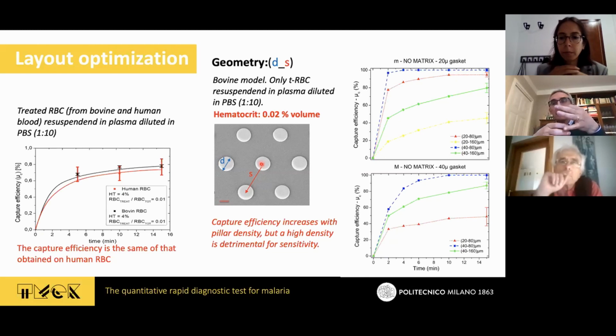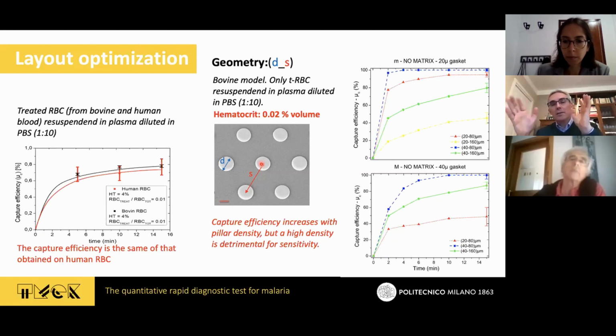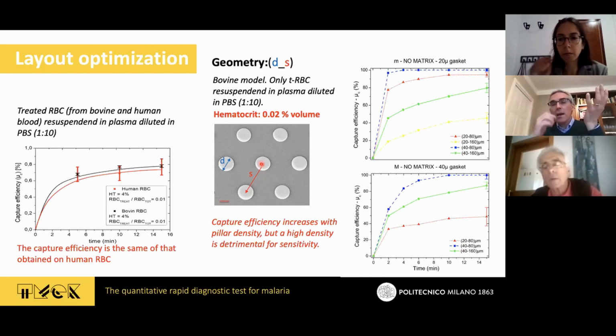So if you increase too much the number of electrodes, obviously you are increasing the denominator of your fraction and you lose the signal. So there is a trade-off between the two things, the capture efficiency and the detection efficiency. That's why we choose this solution, which corresponds to the green curve, which is very similar to the blue one, and it makes the detection easier. Okay. That's the first answer.